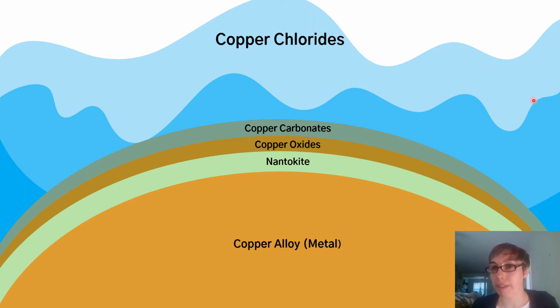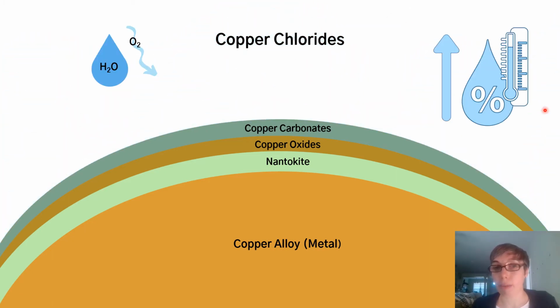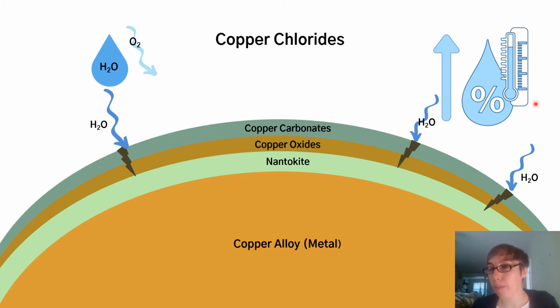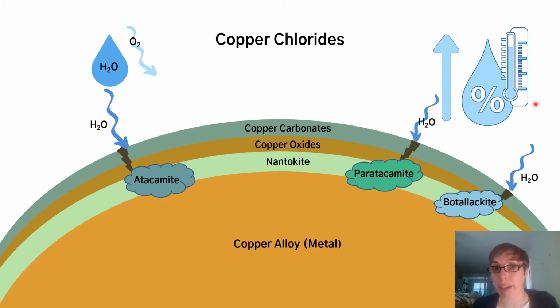And then when the artifact is excavated and re-exposed to atmospheric moisture and oxygen, and maybe there are some cracks in that patina layer that facilitate the transfer of water and oxygen into contact with the nantokite layer, then you essentially reactivate the nantokite, and it keeps corroding and will form hydrated copper chloride compounds like atacamite and paratacamite.